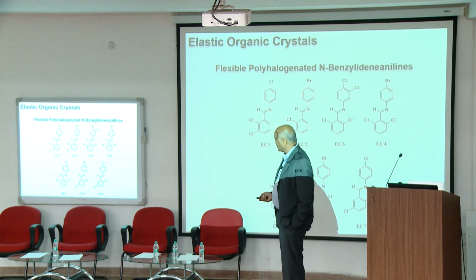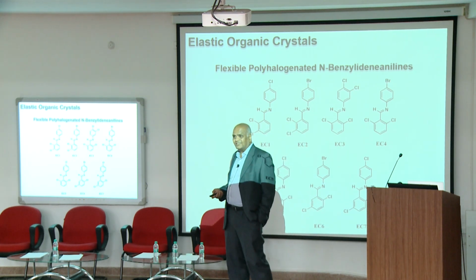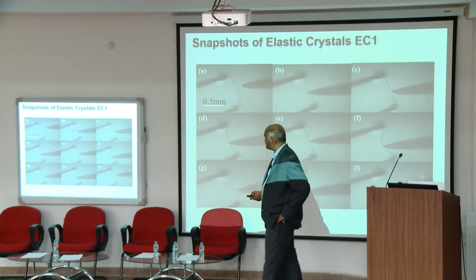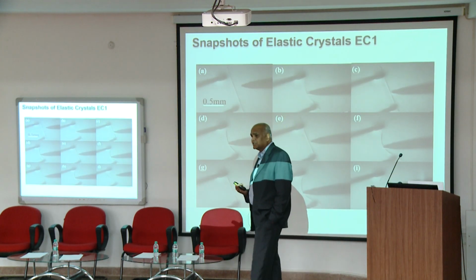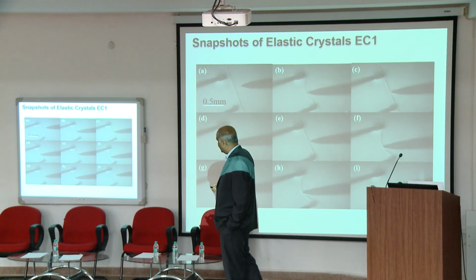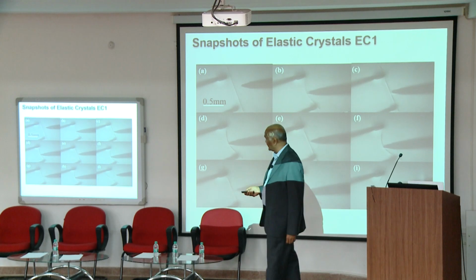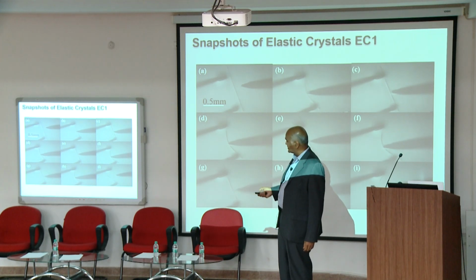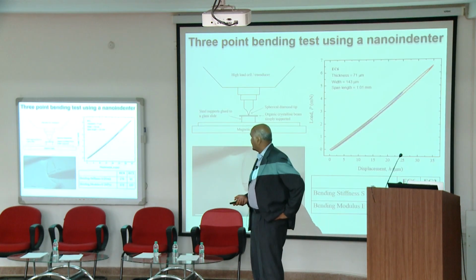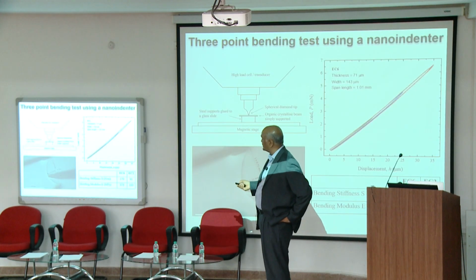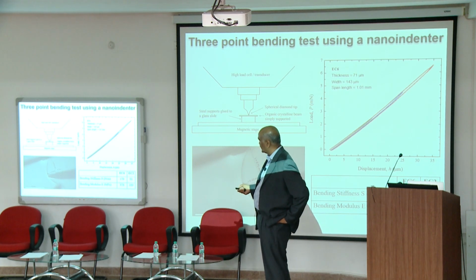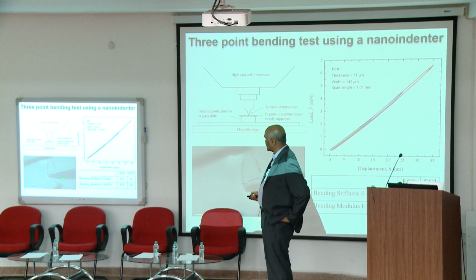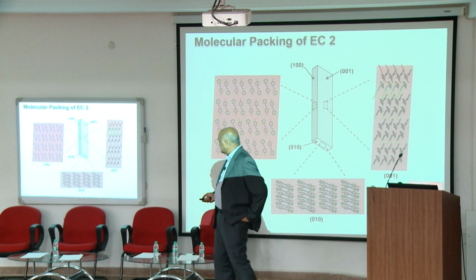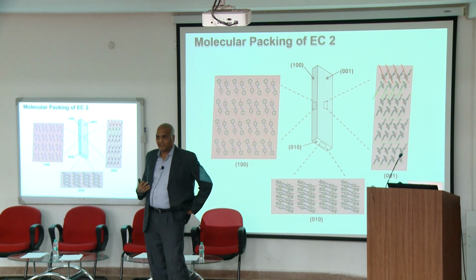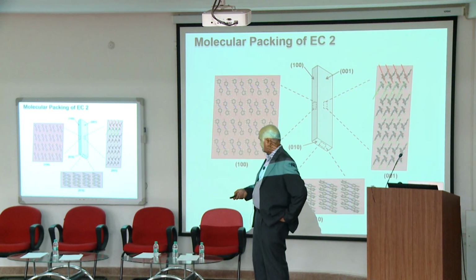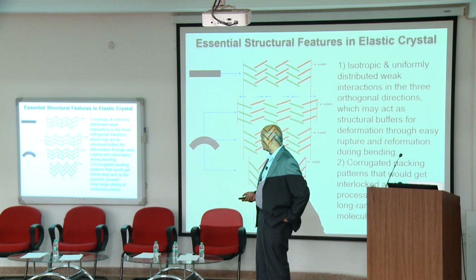And we took a number of molecules like this and crystallized all of them, and they basically have similar crystal structures, and all of them show very good elastic properties. You can see these are thin wires under the microscope, they are being deformed, and you can see that they can go to very large elastic strains. And we also can do the same thing under a nano indenter, now putting it in a 3-point bending configuration and calculate their Young's modulus. Then we look at the molecular packing features in each of these crystals. I will skip very quickly and tell you what the reason is.